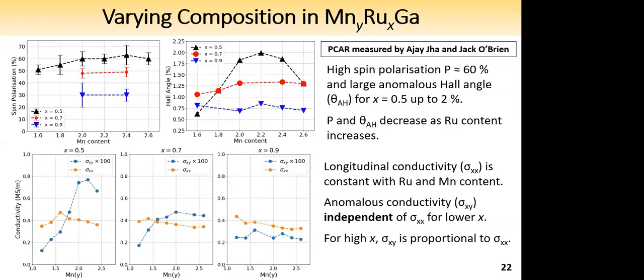Then having a look at the longitudinal and anomalous conductivities, what we find is that the longitudinal conductivity across all series is flat and on average has the same value. If we look at the anomalous conductivity, we see that in some series it is independent of the behavior of sigma xx, the longitudinal, whereas in the last one, sigma xy is proportional to sigma xx. So they both have the same trend. In order to understand these graphs, we need to discuss in a little more detail the two main contributions to the anomalous Hall effect.